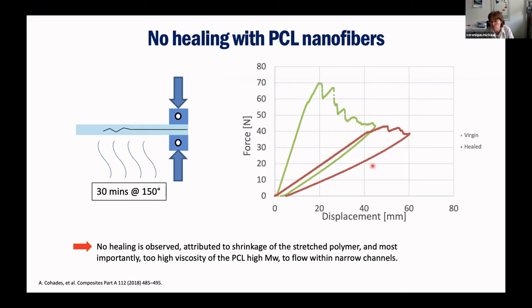So we looked into why this is happening. If you are interested, you can read the paper we did on this. But we found that there are many different reasons. One of it is the stretched polymer fibers that you have in these nanofiber mats. When you heat them up, they are actually quite elongated. So they want to shrink back. And so instead of going out, they were actually shrinking back into their little holes. And so they were not at all going into the crack.